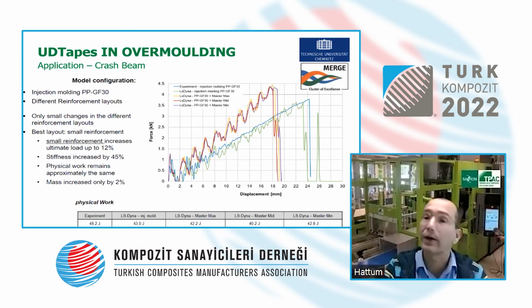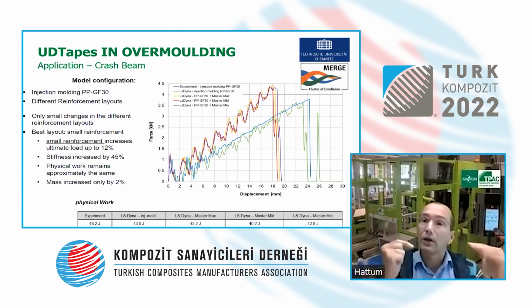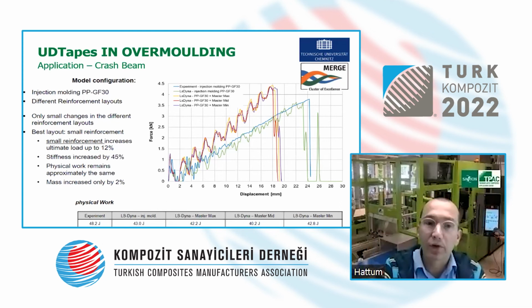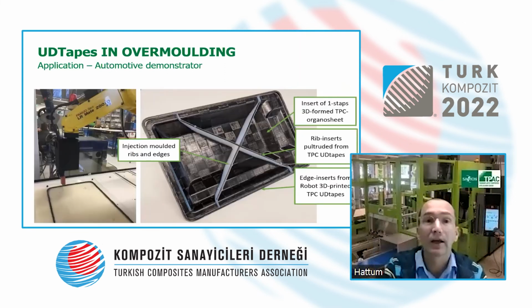Stiffness increase as well, which is good, so you get less intrusion during action, but the physical work, so let's say the energy absorbed by the structure, remains the same. So basically, by introducing small reinforcements, you actually improve the performance of the part at only a minor increase, well, in this case, in weight and costs.